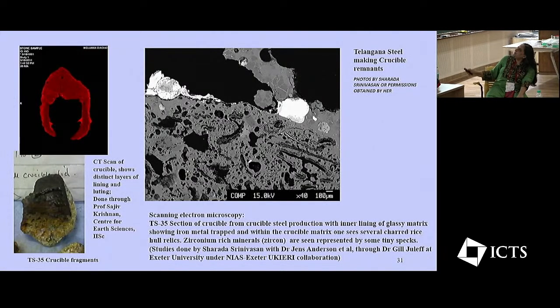And here you see the fabric of the crucible on which we have done scanning electron microscopy. It's quite interesting. Of course, these are the metallic remnants of the iron, and then there's a glassy matrix here and so on. You're also seeing here that they were deliberately adding these rice hull relics into the matrix of the crucible, especially this layer, which needs to be very carbon rich. And that's interesting because the rice hull relics, when they are cooked, become very rich in silicon. In fact, I found some formation of silicon carbide as well in the rice hull relics, which is also a very good refractory. So it points to how this would have helped in carburizing as well as creating a good refractory material, again, using traditional materials.